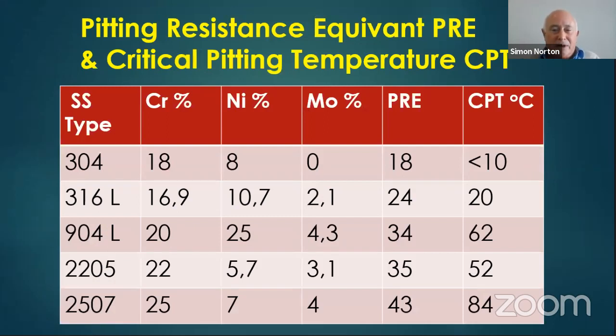So going back and summarizing, if you look on the left-hand side, there are different stainless steel types: 304, 316L, 904, which we call a super austenitic, 2205, which is a DUPLEX stainless steel, 2507, also a DUPLEX. And if you look at the chromium content, that's the key to stainless steel, you'll see that it increases substantially. If you look at the nickel content, you'll see that the DUPLEX stainless steels are very low on nickel, and nickel's a very expensive material. So DUPLEX stainless steels allow you to get amazing performance out of your stainless steel, but without the cost associated